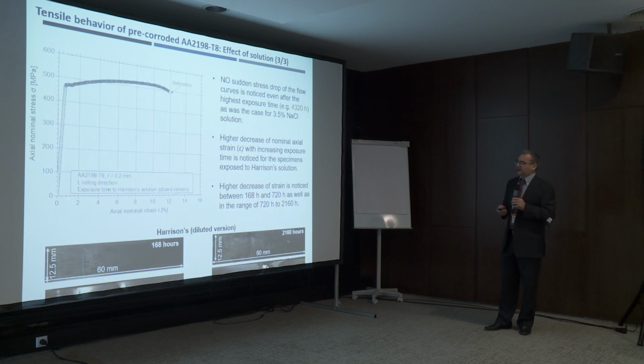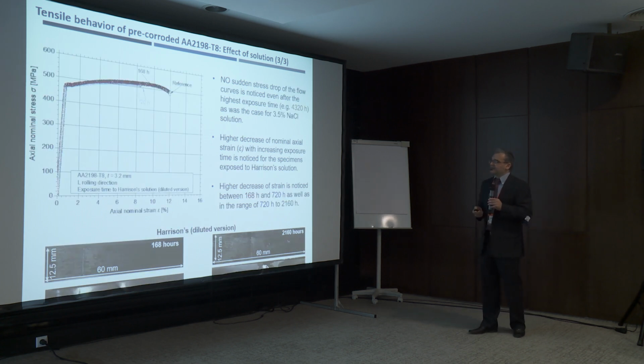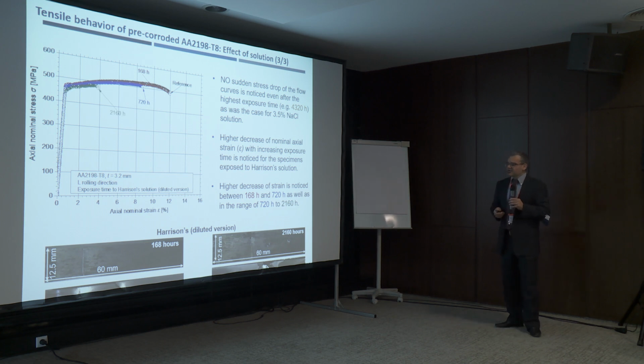And finally, these are the results for the Harrison's solution, showing a gradual degradation of the elongation at fracture with increasing exposure to the solution. Here you can see what is the difference. The difference with the Harrison solution is that you have more localized corrosion, and this was the initiation point in most of the specimens that fractured.